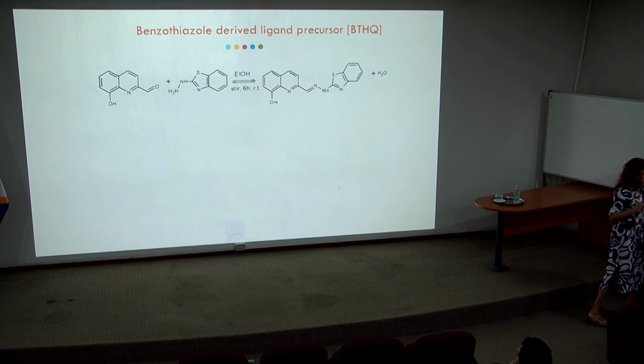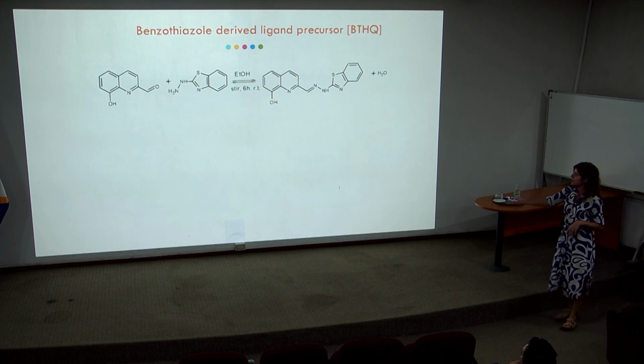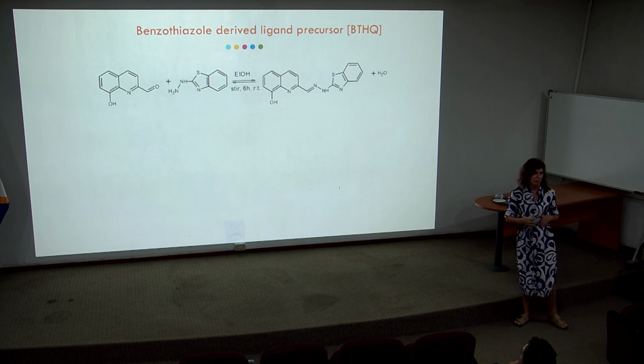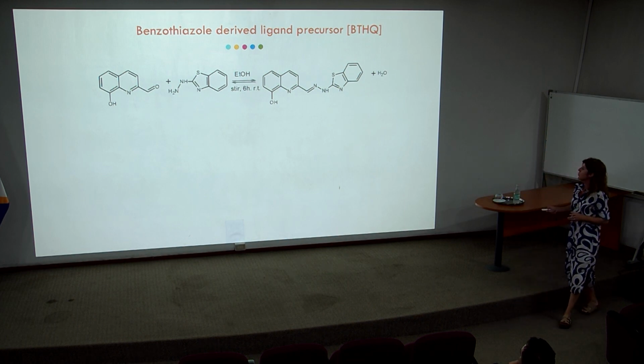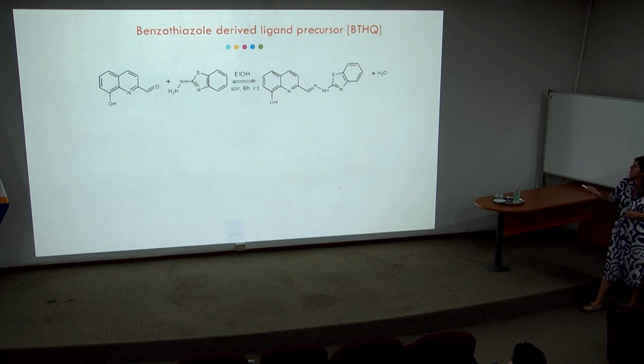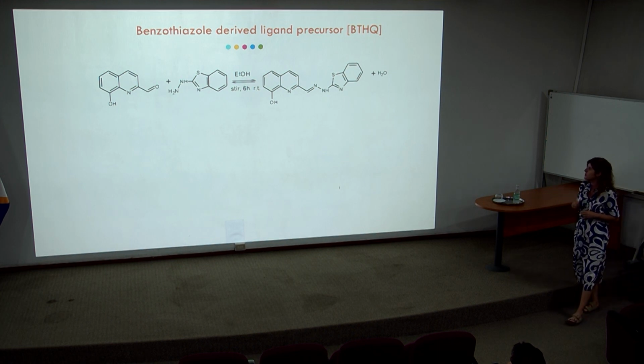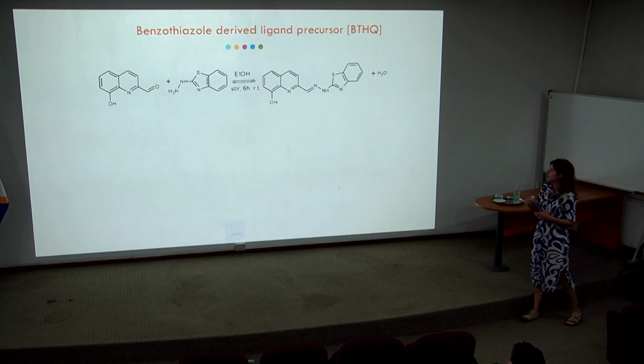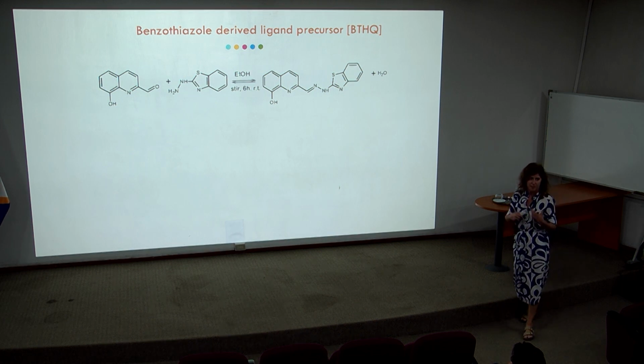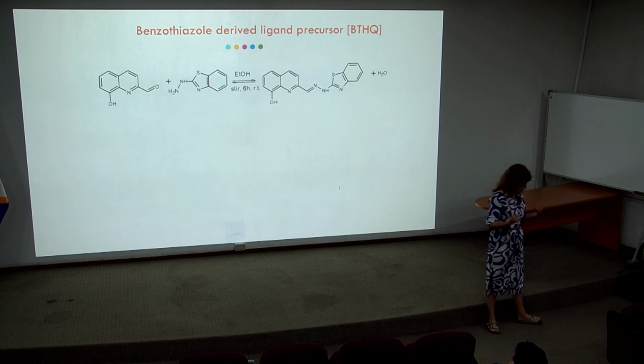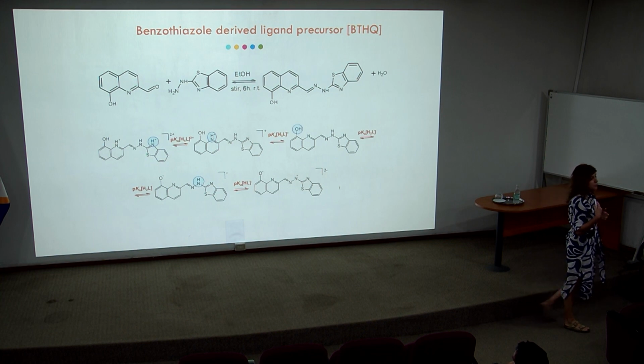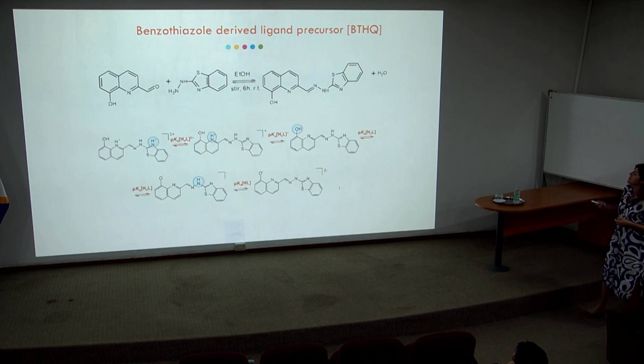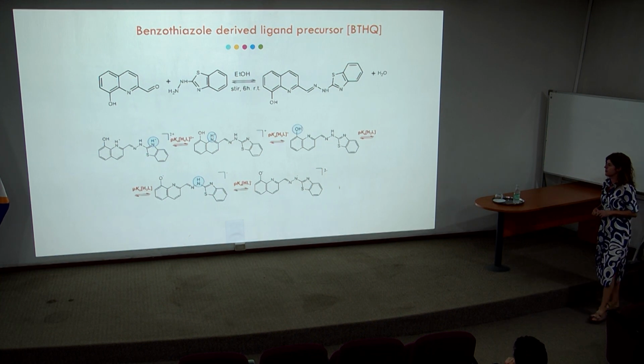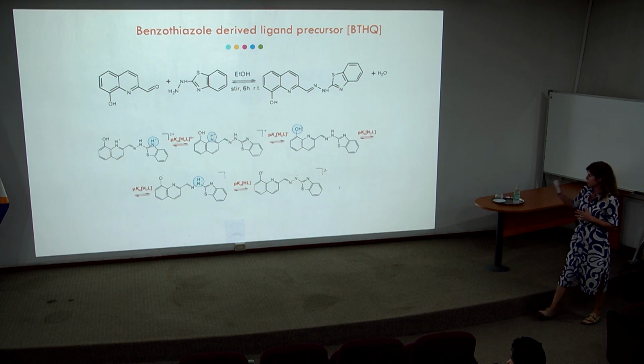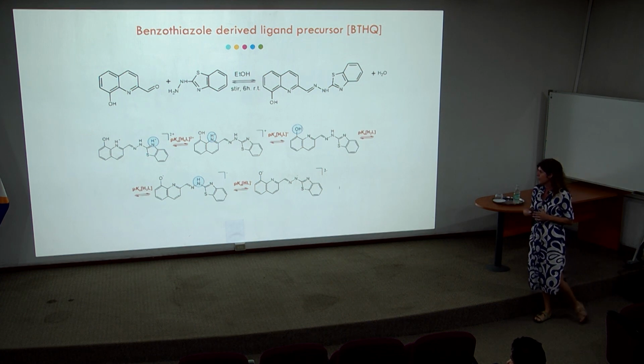We decided to couple the 8-hydroxyquinoline with this benzothiazole because this unit also shows some bioactivity. So it's a simple reaction, the formation of the ligand that we then characterize by the usual techniques, and something that we now try to do is to determine the protonation constants of the ligand. We do this by UV-visible spectroscopy, in which we change the pH.